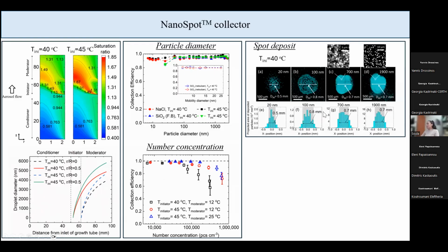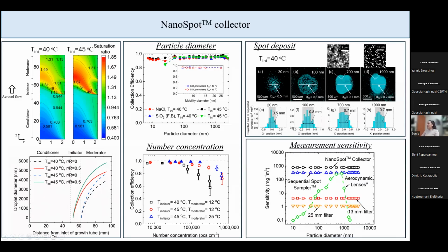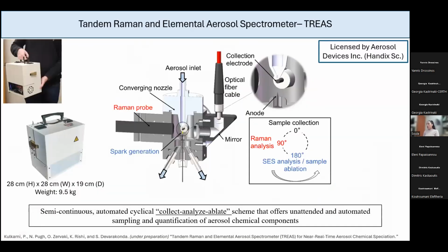And again, I got the spot deposition area for different PSL sphere sizes from 20 nanometers up to 2000 nanometers. We get a similar deposition area no matter the initial particulate size. And again, like before, I was able to calculate theoretically the sensitivity that we can get when we use the Nanospot collector, which is better than the other conventional aerosol techniques that we generally use. And now I'm gonna move on to some stuff that I did for my postdoc.